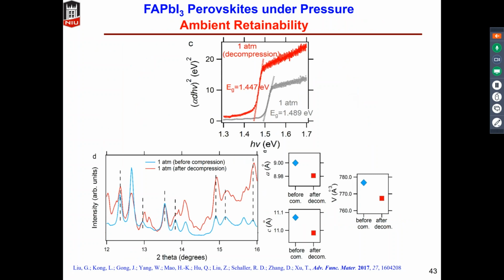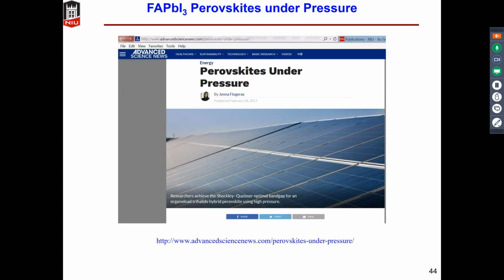And very interestingly, when we remove the pressure, so decompression, we found that the band gap narrowing does not come back to the original value completely. There's still some remaining band gap narrowing effect. So this is the band gap before compression, and this is the band gap at 1 atmosphere, but after decompression. You see that there's a gap between them, so there's some ambient retainability of this band gap narrowing by compression. So this work was highlighted as perovskite under pressure by Advanced Science News.